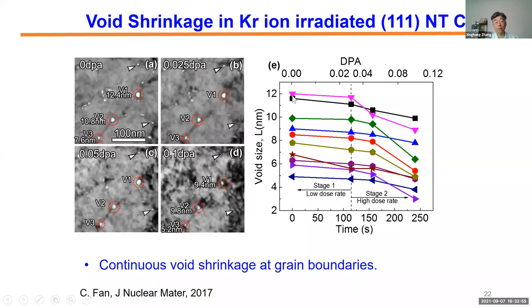And if you look at the statistics, the void size versus the radiation time, you find out, depending on the dose rate, if I have a low dose rate, it changes very little. But when you accelerate the dose rate, the void size decreases pretty rapidly, in some cases drastically. So we have seen, in this case, the void shrinkage phenomenon. That was confirmed in this nano void, nano twin copper.